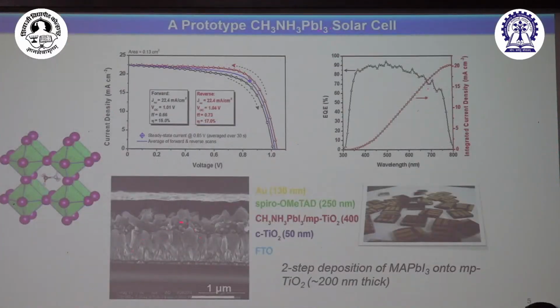Okay, this is a cross section of the solar cell that we have, and remember, you make an FTO electrode, conducting glass electrode, used all the time. If you take a cross-sectional image, the big crystals you see here are your FTO, the conducting tin oxide layer. Look at the thickness here, okay?